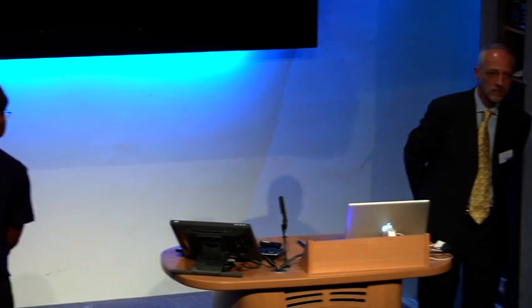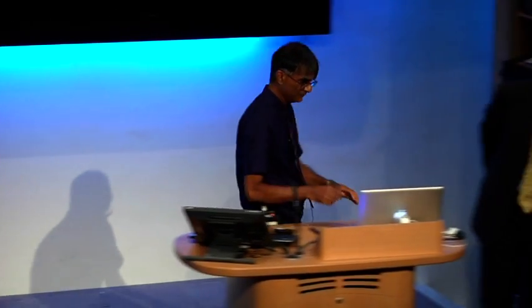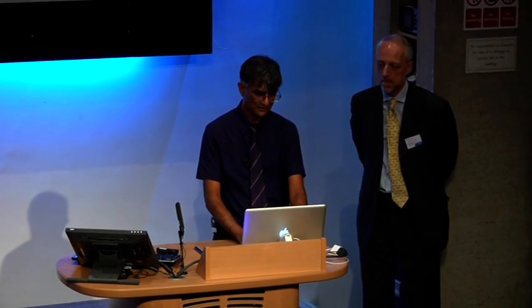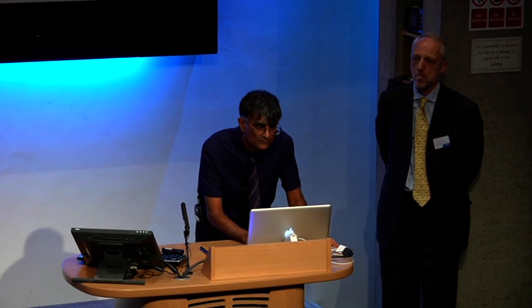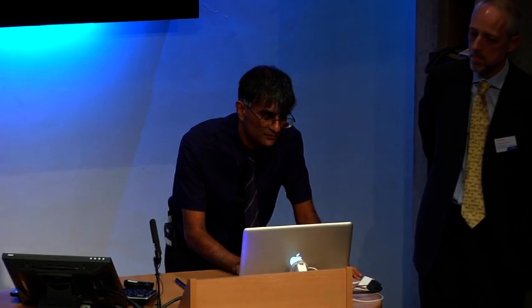You have a line in one direction. Is the material direction sensitive? No. If you look at the optical micrograph, which I show deliberately, the trouble with structures which are very fine is that you have to look at a very narrow region. This is the optical micrograph. This is an isotropic material. But when you focus on a very small region, you see that direction.